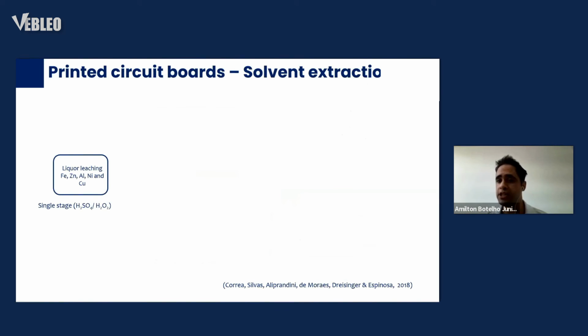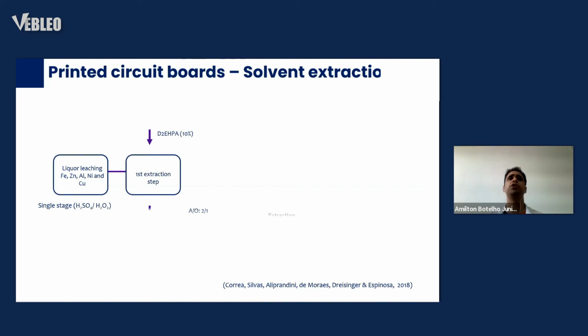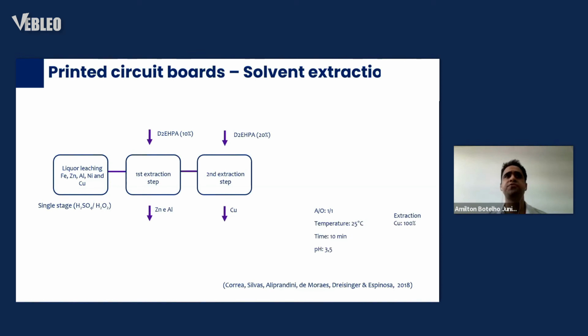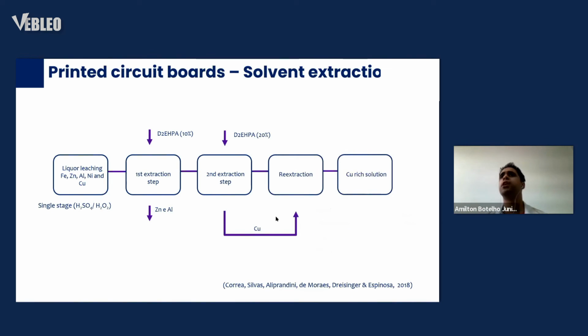And then after the leaching, copper separation can occur by solvent extraction using a few organic extractants such as D2EHPA, a type of organic extractant, in several steps, first to remove zinc and aluminum, and then to obtain copper. And after the re-extraction, the stripping procedure, to remove copper from the organic phase to the aqueous phase, it's possible to obtain a copper-rich solution with low concentration of impurities. So that's important to prepare copper sulfate or metallic copper.